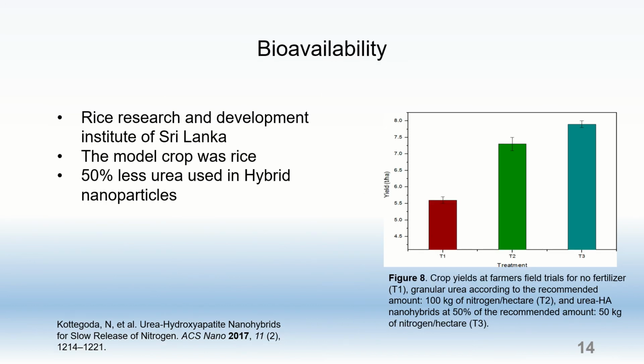The bioavailability of this slow-release urea-hydroxyapatite nanohybrid was evaluated at the Rice Research and Development Institute in Sri Lanka, with rice as the model crop. The field testing was then extended to certified farms. The field trials revealed that a savings of up to 50% in urea consumption was attained by using the urea-hydroxyapatite